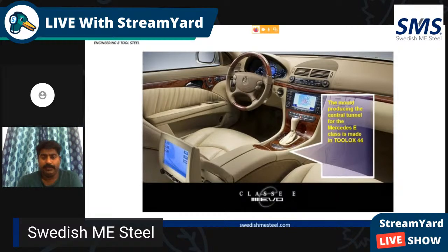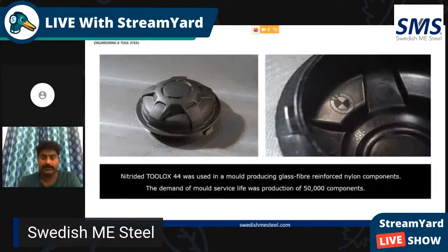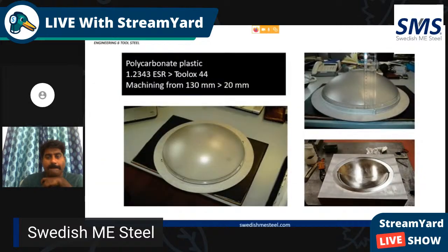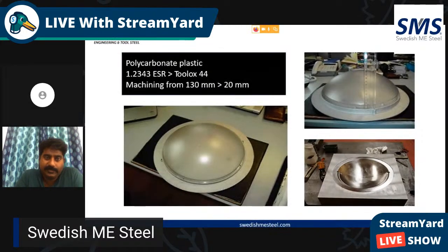And Toolox 44 has again been used in the central tunnel of Mercedes. And nitrided Toolox 44 is used in glass fiber reinforced components. The demand for the mold service life was production of 50,000 components, which was easily achieved. And this is in polycarbonate plastic, in which the earlier material was H13 ESR. You can find that Toolox has replaced it, but not only that, there is really extremely high machining involved.